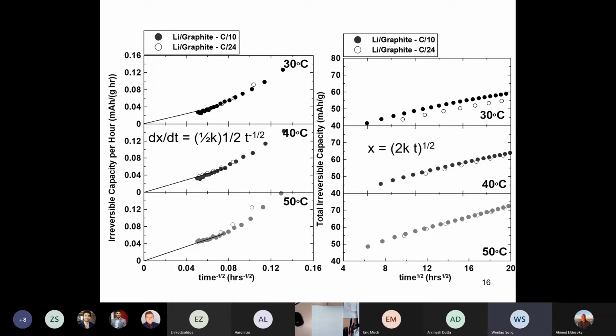Jeff? Yep, go ahead. Yes, so for different additives, if you do the experiment, does the K value differ for different additives? Yes, absolutely. When you put different additives in, all of these slopes can change very much. Absolutely. Can we say that if for a certain additive the K value is very small, it's a better additive? Yeah, in terms of making a very good SEI on the graphite side, yes. Okay, thank you.